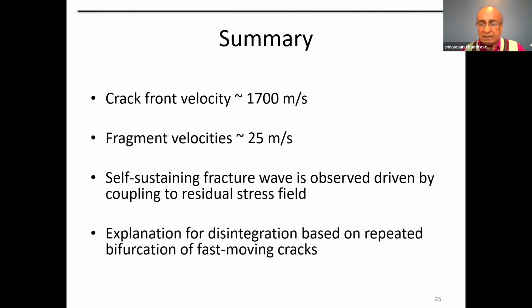So, a summary of the work so far: cracks propagate with high velocity, reaching a threshold of about 1700 meters per second. There's a self-sustaining fracture wave from the tail to the head. And then we think we observed evidence of bifurcation, and we think we can explain the disintegration based on bifurcation of these cracks.